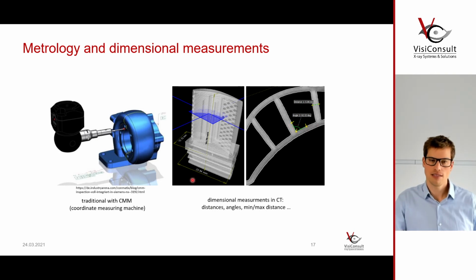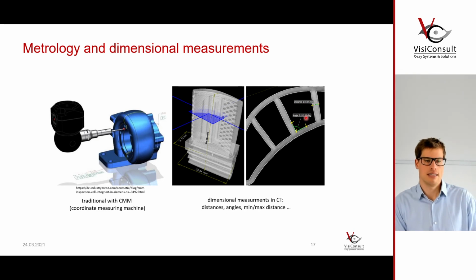So with the CMM, yes, you can measure outside points. You can move the measuring probe towards different areas of the part. But what you cannot do is measure angles on the inside. You cannot measure distances on the inside. So this is where CT really shines, especially with additive manufacturing, because that's hands down, we are not using additive manufacturing to design simple parts that is sufficient to measure from the outside. We are using additive manufacturing to build parts that are complex and that have internal passages and lattice structures. So you would need a technology that allows you to measure that throughout the inside and outside.